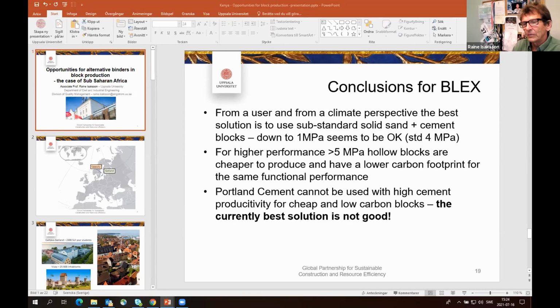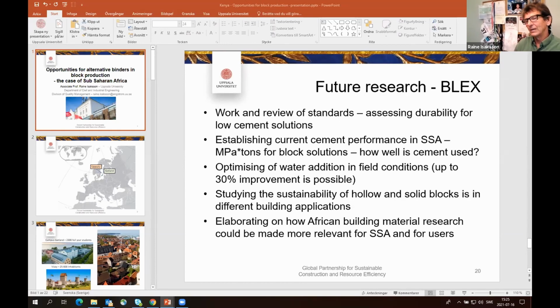So my conclusion after all this, and I should of course have come up with it earlier, but maybe I'm a slow learner, is that Portland cement really cannot be used with high cement productivity. If we go down to these low levels of cement percentage, we use only a fraction of its building capability. If we increase the cement again, then we produce strength which is not needed. So the currently best solution is not a good solution, which then brings me forwards.